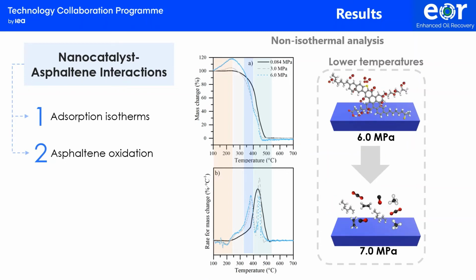When the pressure rises, different changes are evident in the mass change and mass change rate profiles. First, an increase in mass at low temperatures is observed, attributed to oxygen chemisorption in the asphaltene molecular structure. Then there is a decline in the sample mass, mainly associated with desorption and changes in the oxygenated structures formed.